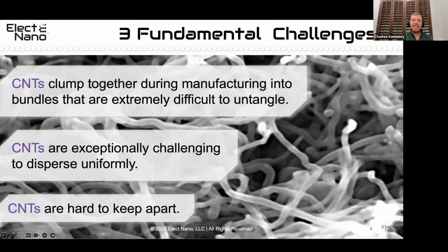And then in some cases, you'd centrifuge it and try to separate out all the nanotubes that were not dispersed well. And then you're left over with a very dilute solution of maybe a few nanotubes floating around. And then you run to the SEM and you hunt around for that one nanotube that's well bonded to the epoxy, and then you go publish a paper on it.